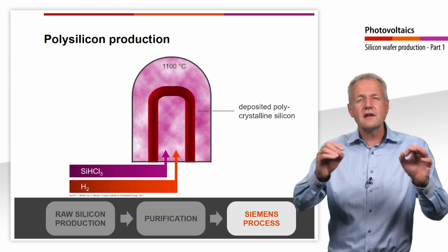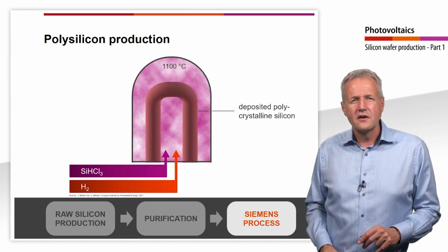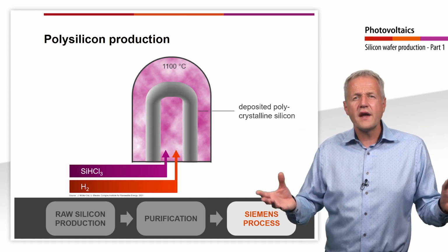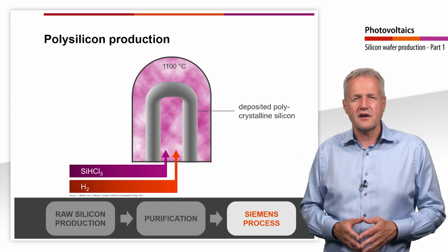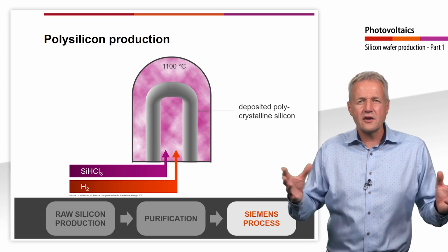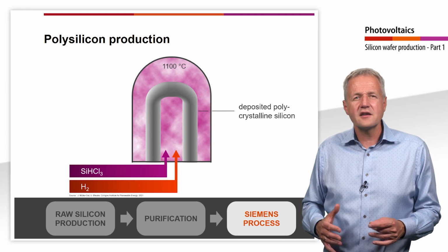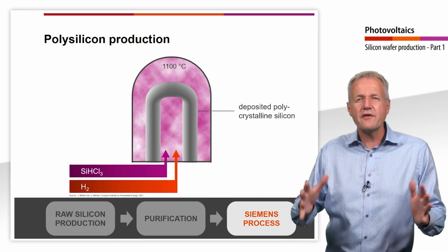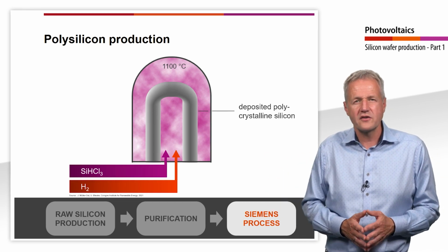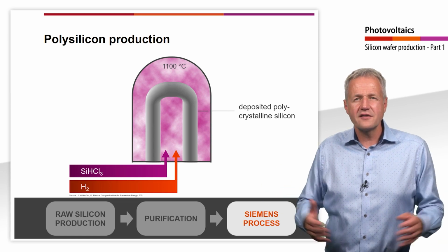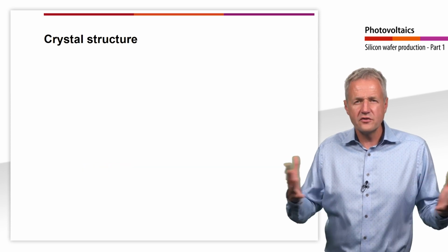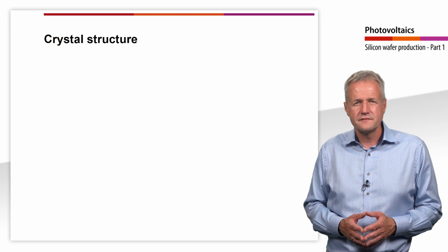now gradually silicon deposits on the rods, which grow in this way to form thicker rods of polysilicon. In these polysilicon rods, there is at most 1 foreign atom for every 1 billion silicon atoms. The purity of the silicon is now sufficient for use in solar cells.